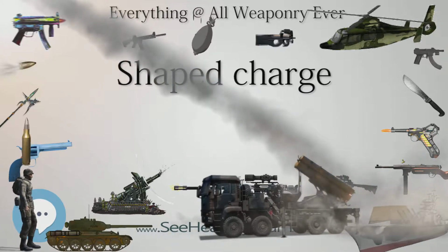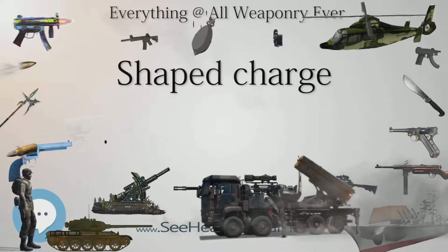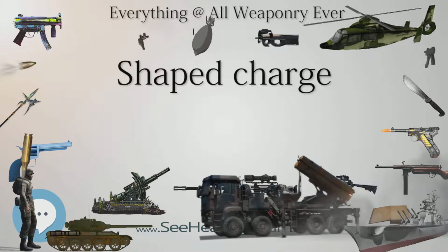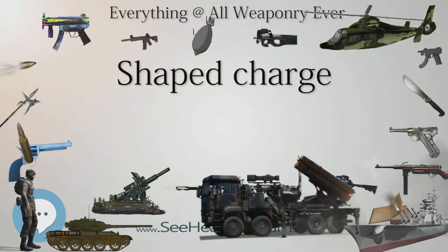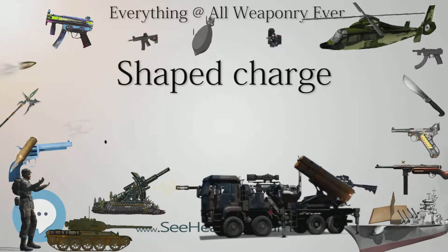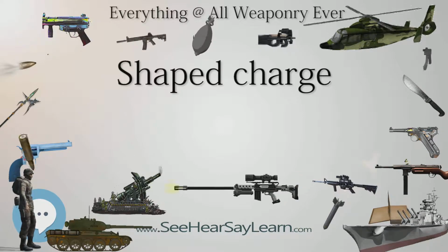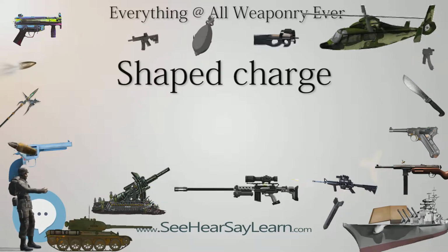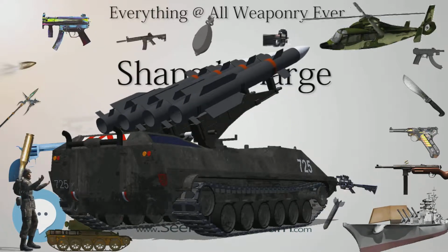Liner. The most common shape of the liner is conical, with an internal apex angle of 40 to 90 degrees. Different apex angles yield different distributions of jet mass and velocity. Small apex angles can result in jet bifurcation, or even in the failure of the jet to form at all. This is attributed to the collapse velocity being above a certain threshold, normally slightly higher than the liner material's bulk sound speed. Other widely used shapes include hemispheres, tulips, trumpets, ellipses, and biconics. The various shapes yield jets with different velocity and mass distributions.